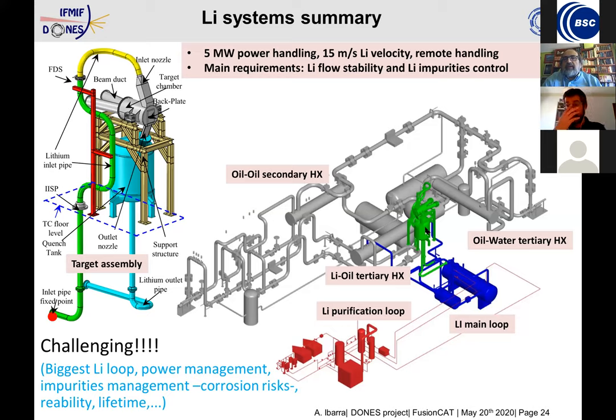There is an additional small detail that makes things even more interesting, that is that due to the nuclear reactions that take place, some transmutation products are produced inside the lithium, like some tritium, some beryllium, some other things. And besides this, the lithium corrodes the walls of the loop a little bit. Not too much, it's not a problem, but some impurities appear in the lithium. And besides this, the lithium can be contaminated by the air atmosphere and things like this.